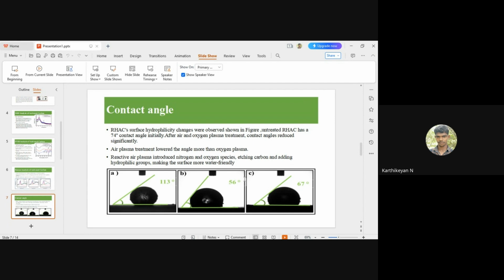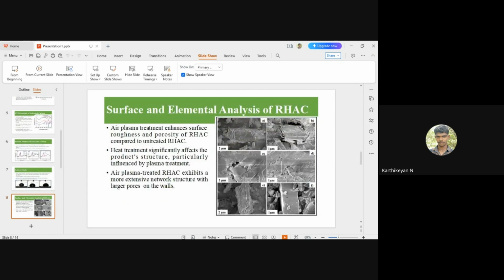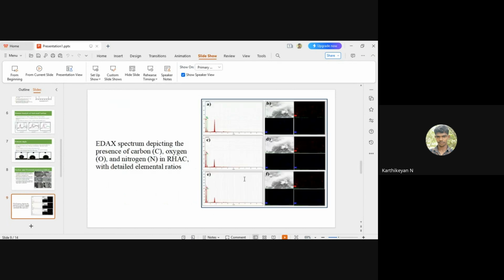making the surface more water friendly. Now the surface and elemental analysis of RHAC. The air plasma treatment enhanced the surface roughness and porosity of RHAC compared to untreated RHAC. The heat treatment significantly affects the structure, particularly when influenced by plasma treatment. Air plasma treated RHAC exhibits a more extensive network structure with larger pores on the walls. The EDS spectrum and color mapping show the presence of carbon, oxygen and nitrogen groups in RHAC.